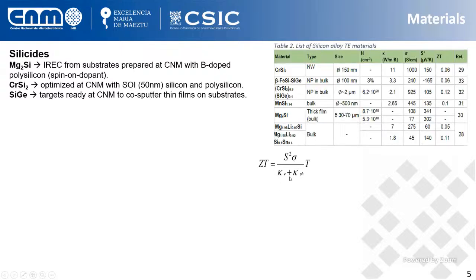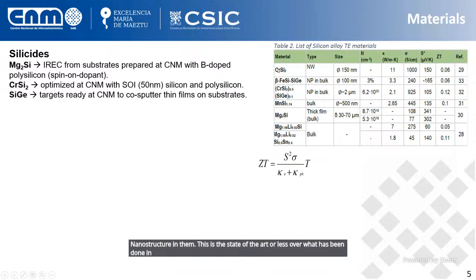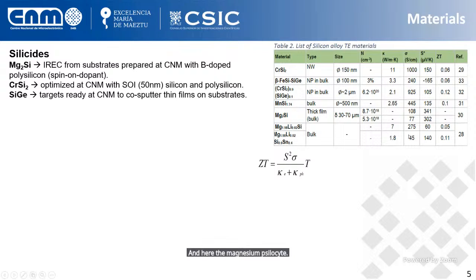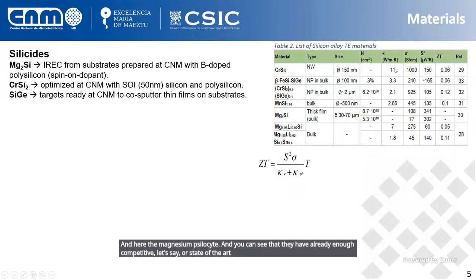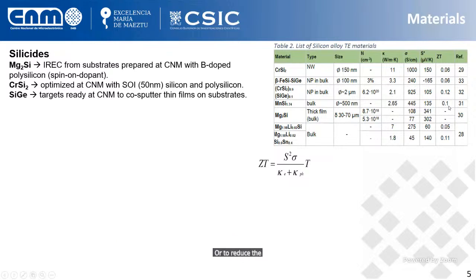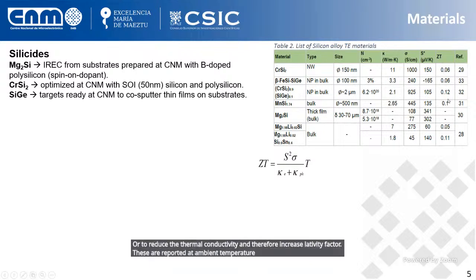Okay, this is the state of the art, more or less, over what has been done in silicides. And you can see here on the top the chromium silicide, and here the magnesium silicide. And you can see that they have already competitive, let's say, or state-of-the-art electrical conductivities, and they have low enough thermal conductivities. We want to reduce them further by using tens of nanometer thick layers to reduce the thermal conductivity, and therefore increase the ZT factor. These are reported at ambient temperature, if I recall right, but if you increase temperature, these figures of merit are even better than these ones.